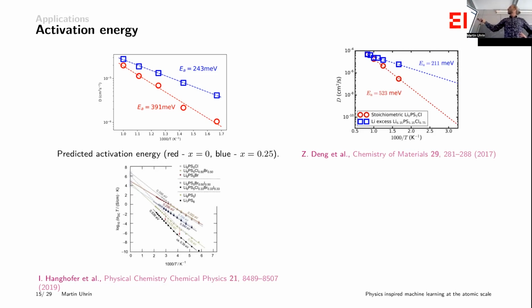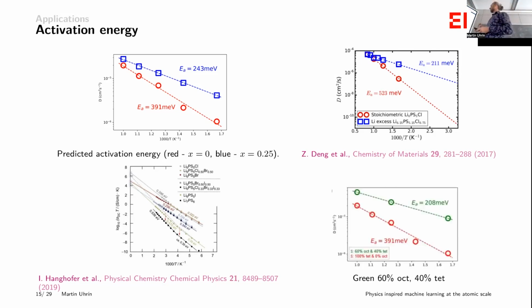The reason this number is different, as we found out, is that there are different ways you can occupy the sulfur sites in this crystal structure. There are octahedral and tetrahedral sites, and you can occupy them in different ratios, and that will change your conductivity. This one was actually in a different phase, we think, than what we were working with. So I asked GE to go back and change these occupations to be more like what they were likely seeing in their experiment, 60-40 for this green line. And now, having the structure that we think is the corresponding one for this experiment, the error is again bang on. It's as good as I think it could be.